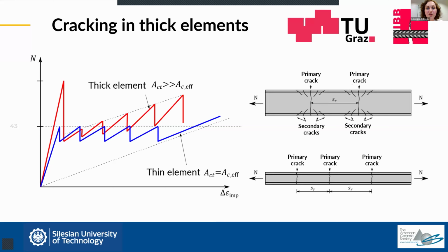In such an element, you need, of course, a much higher force to produce a crack because the area is higher. But at the same time, the behavior during cracking is different because, since such a large amount of force is required to cause subsequent cracks, it is very hard to produce another through crack. On the contrary, we rarely observe another through crack, but the first crack is accompanied by a series of secondary cracks that only affect the effective tensile area, so the area where reinforcement is active.